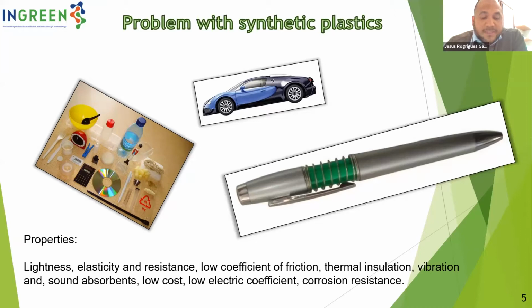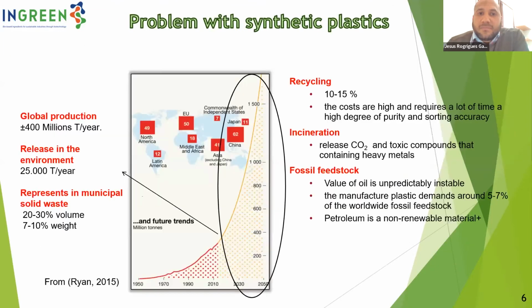This problem with the plastic synthetics causes its accumulation in the air, causing very serious pollution problems in the environment. In this slide, we can see that the global production was around 400 million tons per year in 2015 and increases as the years go. The efforts to control this problem, for example recycling and incineration, are not effective to reduce the plastics pollution. And it's very important to say that this material is of petrol oil origin, and someday the petrol oil ends in the world.